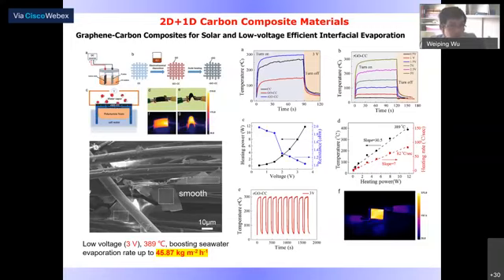Using electrochemical deposition, I deposit graphene from graphene oxide on this carbon fiber, like this two-dimensional textile. Then I can enhance the heating performance, and this type of heating device only requires a very low driving voltage, from 0.5 volt to 3 volt. The heating also shows very impressive performance. Within 90 seconds, 120 seconds, we can reach a very high temperature around 300 centigrade.